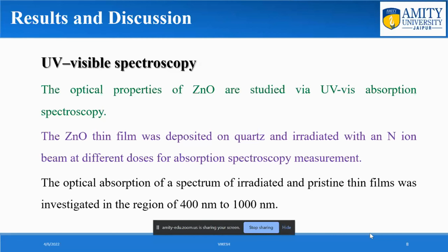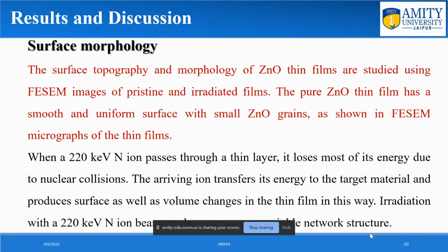The surface morphology. The surface topography and morphology of ZnO thin film was studied using FESEM images of pristine and irradiated thin films. The pure ZnO thin film has a smooth and uniform surface with small ZnO grains, as shown in FESEM micrographs of the thin films.